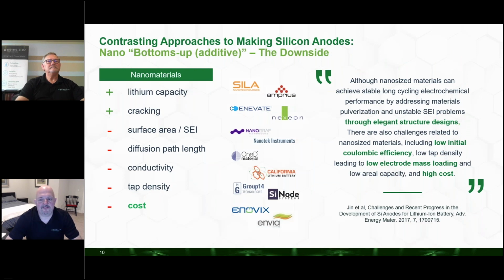So as we look at this, it's not just us saying this. This comes from one of the most prominent review articles in the last couple of years. This group looked at all the different technologies that had been done in silicon anodes over the last 20 years. And they came to the conclusion that, although nano-sized materials can achieve stable cycling performance by addressing pulverization, so these other materials are able to start off with small particles and not crack, and then combine those particles into elegant structural designs to try to counter this chemical coating problem or surface reactions problem, they lead to other problems in the battery. And these other problems in the end lead to a high cost.